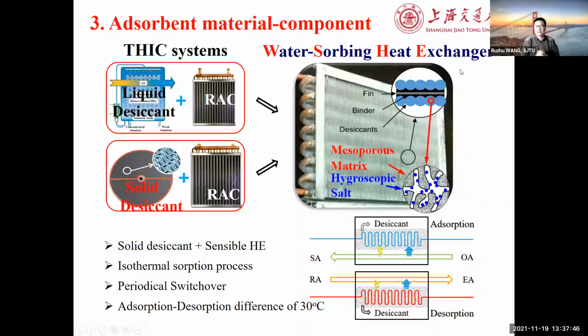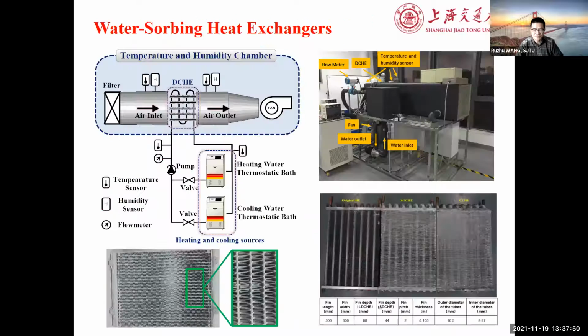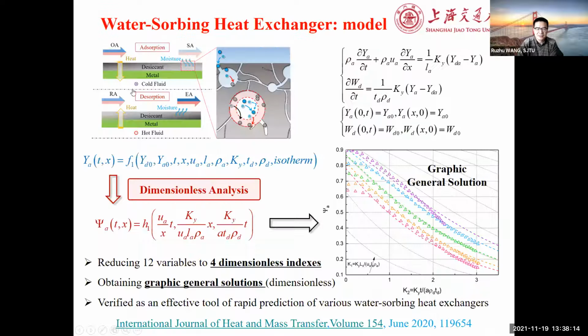So this was developed first by Shanghai Jiaotong, and then we did some research. And this just shows a desiccant heat exchanger in the air duct. So we have heating and cooling, and normally have about a 30 degrees temperature difference. So cooling could be about 15 degrees and heating at about 45 degrees. So this just shows the original heat exchangers, and then we coat them with desiccant and do the test. So this also shows the measured data.